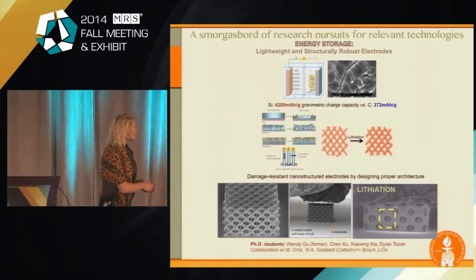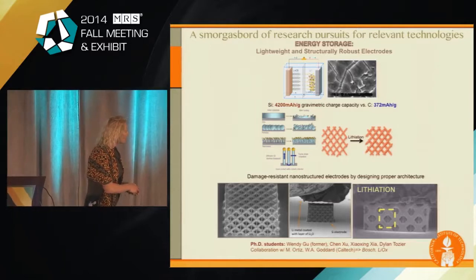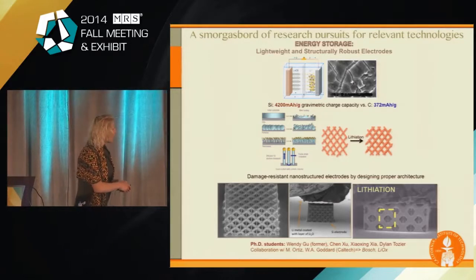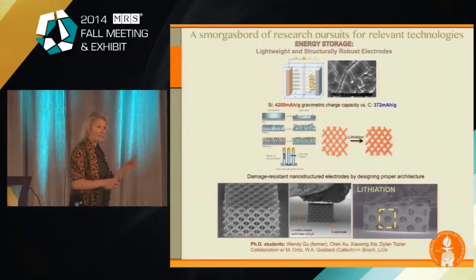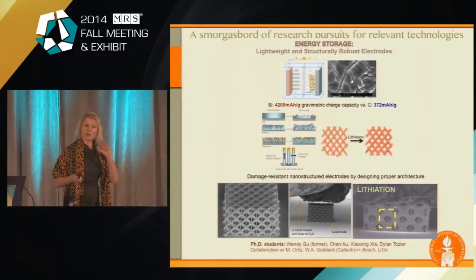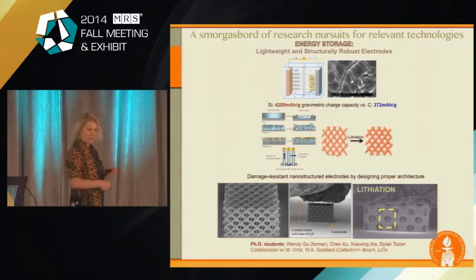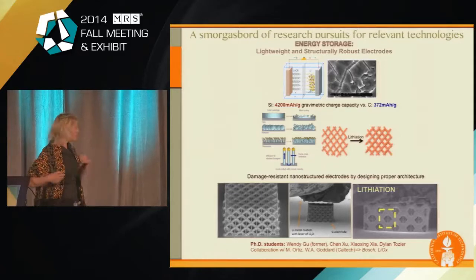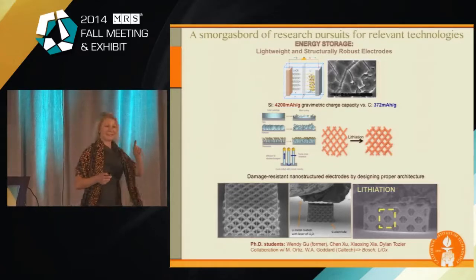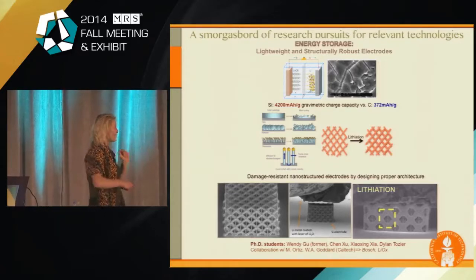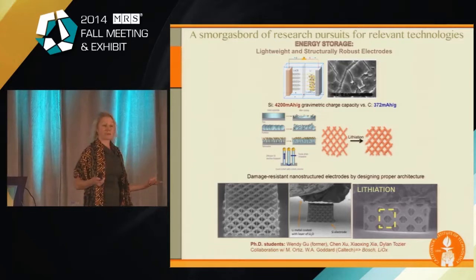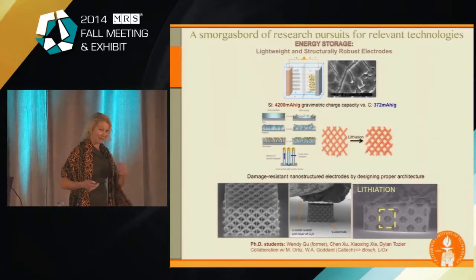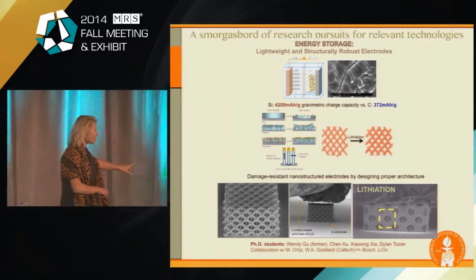And so this is where we got this idea. What if we used a nanotruss, like I showed before, and then lithiated it, because it's effectively a nano ribbon, right? And if it's a nano ribbon, we should be able to use this nano size effect without cracking and without catastrophic failure. But this is the part that I was telling you about before. If it's a battery electrode, we have to be able to collect the electrons, so the core can't be hollow. So this is where the copper came in.